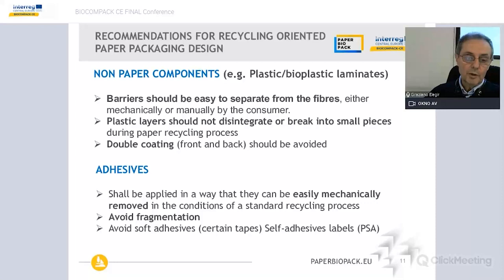Also, double coating should be avoided. By double coating, I mean when the coating is done on the front and on the back of the products. This is not recommended, because when we have a double coating, the water intake is more difficult in the products, and a more difficult water intake means that it's more difficult to disintegrate the products during the repulping.